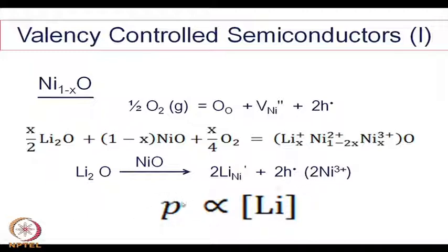and the concentration of the holes p is proportional to the concentration of Li. It is not dependent or controlled either by PO2 or by temperature. So, it becomes more or less temperature independent, except of course the mobility term will change, but the concentration of the charge carrier here will remain fixed by the concentration of lithium.